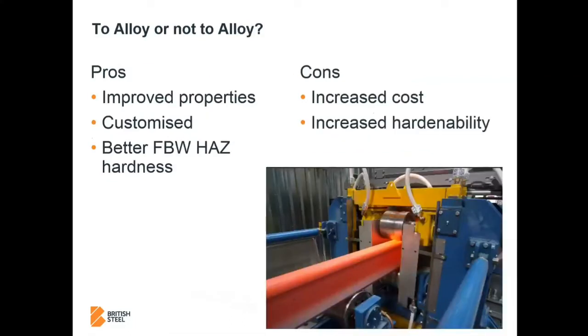So the pros for chromium alloying: you improve the properties, you actually strengthen the ferrite within the pearlite. So you're getting some microscopic performance benefits at the surface interaction. You actually get improved rolling contact fatigue resistance. It's marginal, but it is documented. You can customize your chemistry and your hardness levels a bit more with some of the supplier branded products such as MHH from our former friends in Hayange. You get better flash butt weld heat affected zone hardness.